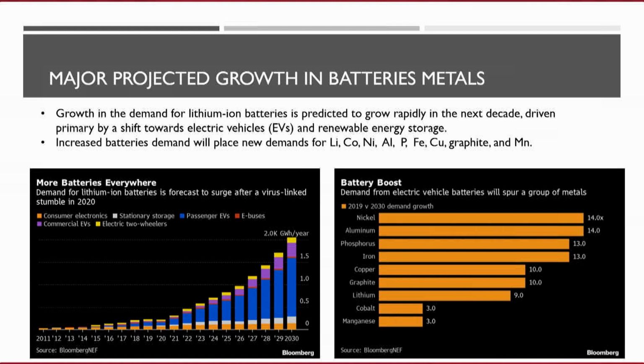So this is driven primarily by a great increase in the demand for battery metals, among which one of the most important is lithium. And you can see that in two ways. On the left, in terms of projected power demand, you can see 2022 kind of in the center there, out to the end of the decade. In 2030, there's going to be an exponential growth. And that correlates to projected increases in the demand of these separate metals you see at the right. So this is from 2019, but we have a many-fold increase in lithium in particular that you can see near the bottom.